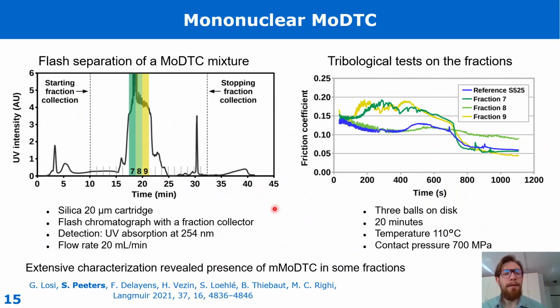So to gain some insight, we separated a commercial mixture of MoDTC by means of flash chromatography, and we characterized all the relevant fractions containing MoDTC. Here the most important ones are 7, 8 and 9. And here we carried out tribological tests to compare the friction reduction properties of all these fractions, and we also compared the results with the commercial mixture.